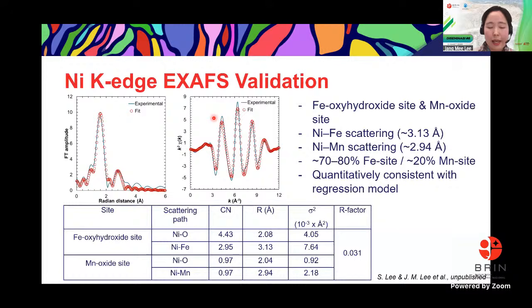So this is the nickel K-edge EXAFS data of the initial laterite ore. And then this is the EXAFS data, and then we did a fitting based on two different crystal structures, which are the iron oxyhydroxide and manganese oxide sites. So we put in two mixed crystal structures and see how it goes. And then you can see the nickel and iron scattering path here. This means nickel is associated with the iron phase. And then you can see another scattering path, which is nickel and manganese. The nickel-manganese scattering path means that nickel is co-associated in the phase of the manganese oxide, which is the asbolane. So we did a fitting, and then you can see the coordination number here.